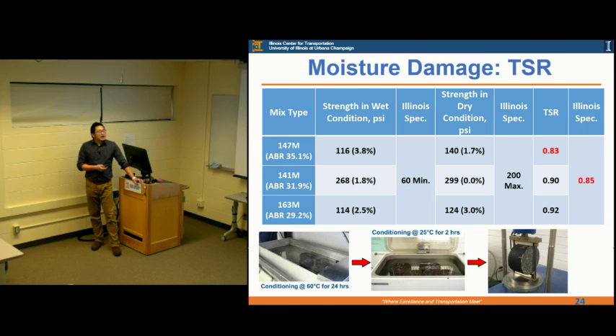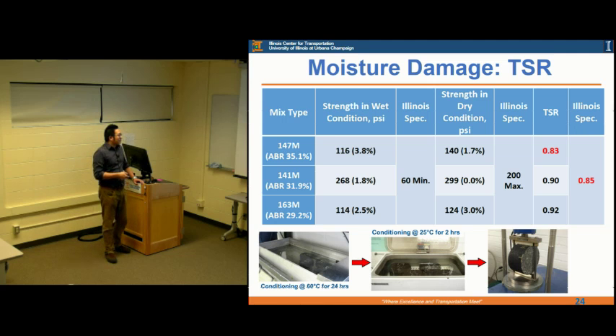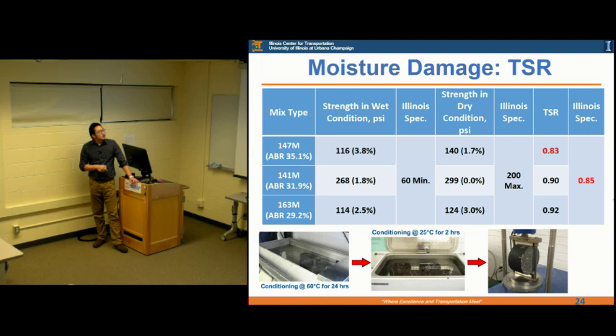But based on this criteria, they are all very good in terms of rutting resistance. And also moisture damage, TSR. This is also in the mix design stage—you have to verify whether these mixes are good in terms of moisture resistance. So basically we are using TSR, tensile strength ratio. You have your conditioned strength and your dry condition strength, and you take the ratio. The minimum should be more than 0.85, but this one is just less than 0.85. Other than that, they are all pretty good in terms of moisture damage.